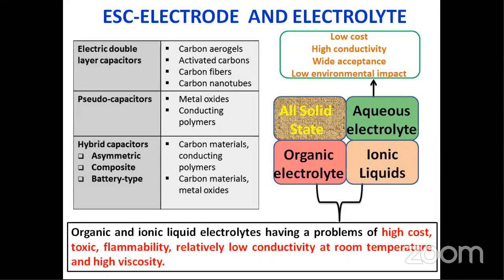By the way, the energy density is equal to half CV squared. So if the voltage window of your system is enhanced, then you can increase the energy density. But the problem with organic electrolyte is that its charge storage is very low when compared to the aqueous electrolyte. I always prefer the aqueous electrolyte because of its wide operating temperature, and the self discharge is also very low for aqueous capacitors. Another thing is that the conductivity of aqueous electrolyte is very high, and it can give a high capacity for EDLC capacitors. That's why I always prefer aqueous based electrolytes for my studies, of course.